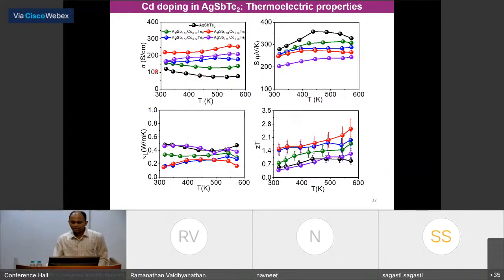So now this is the total thermoelectric data. This is electrical conductivity. This is the control data, AgSbTe2. When I do cadmium, 6%, the maximum limit of solid solution, the electrical conductivity is high because of the delocalization of the electronic states, and the thermal conductivity is low because of the nanodomain formation, which scatters the phonon, also softening of the phonon. And with that, we get a ZT of 1.5 at near room temperature and 2.6 at high temperature.